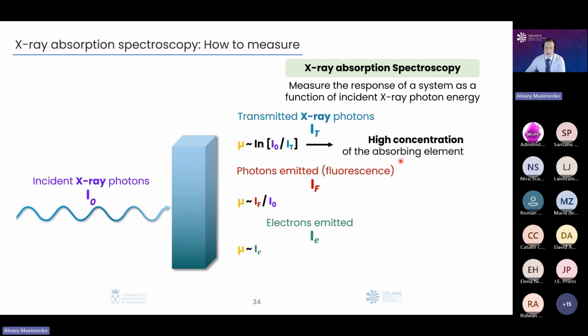And depending on what kind of material you are investigating, for example, if you have a high concentration of absorbing element in your material, then in most of the cases you need to measure it in transmission mode. When you have a low concentration of absorbing element, for example, some kind of intrusion or some kind of a small additive to your compound, you will use a fluorescence method. And if you are interested not in the bulk structure of your absorbing atom, but you would like to investigate what is going on the surface, you will measure this current, which is excited by the incident X-ray photons.